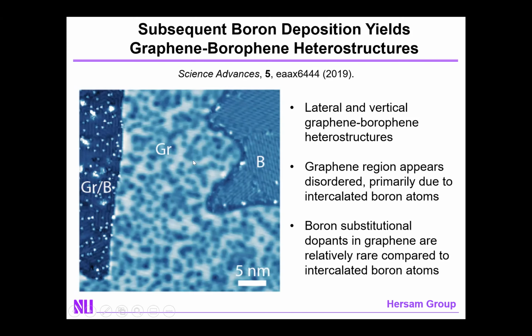And if that boron, which is intercalated under the graphene, got dense enough, it could begin to nucleate into borophene itself and thereby form a graphene-borophene heterostructure vertically, where the boron is underneath the graphene, even though the boron was grown secondly. And all three of those cases are seen in this one STM image.